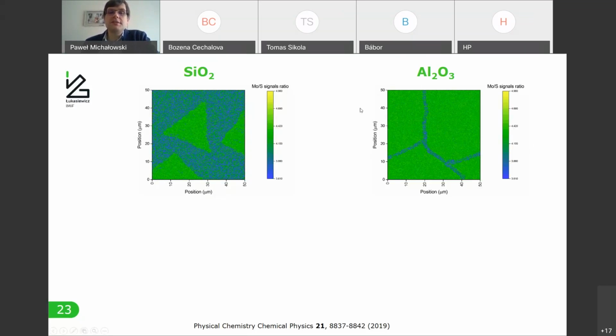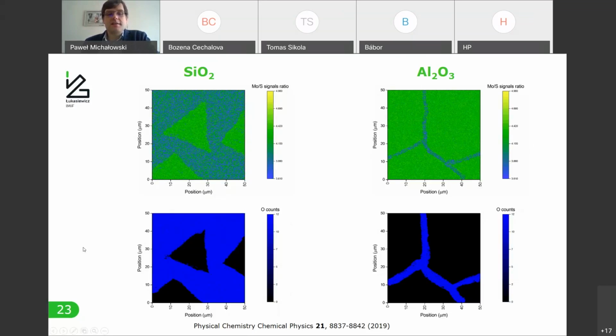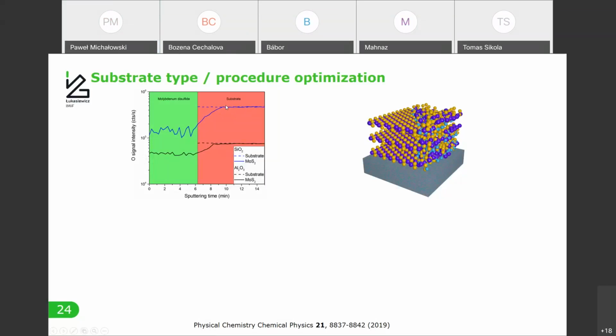And we also included the oxygen analysis shown below. And here you can see that we cannot detect any oxygen in the positions where the high quality material is present, but there is a lot of oxygen everywhere else. In the depth profile, we showed that there is a clear oxygen release from the substrate which contains oxygen, as you can see here when compared to the normal substrate without the molybdenum disulfide film. And thus the oxygen can diffuse into the layer, and that's why the quality of the material is not perfect.